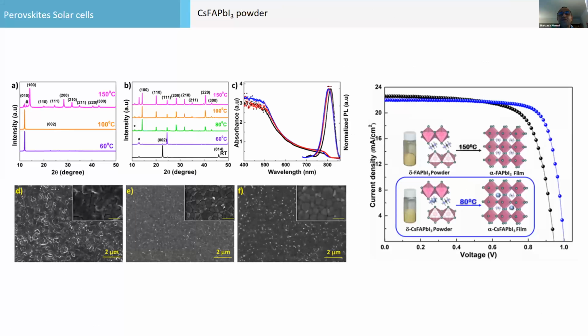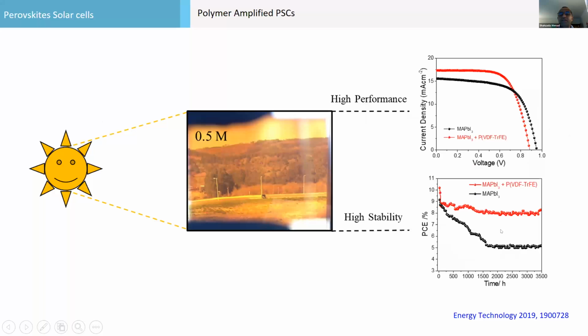The recent work is that we are also working on FA, because FA has a higher onset and also there's no phase transition. Methylammonium has a phase transition at 85 degrees centigrade, which is a very low temperature. So we are working on pre-synthesized FA powder, and we have achieved improved performance in the photovoltaic devices.